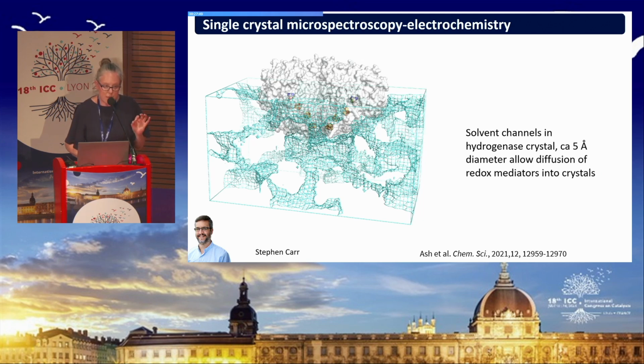And the mediators are able to diffuse into water-filled channels within the protein structure. So Steve prepared this image showing the unit cell for hydrogenase with the hydrogenase molecule and the water-filled channels which contact the sort of edge of the crystal with the surface of the protein where the iron sulfur clusters allow electrons to exchange, so that you can equilibrate right through to the active site very rapidly within seconds to minutes of applying a potential at the electrode surface. The crystal doesn't have to be actually touching the electrode, it's just sitting in that solution in contact with the electrode. We did find we got some redox control if we didn't have the mediators there, but it was very slow, so they helped to speed up that redox transition.